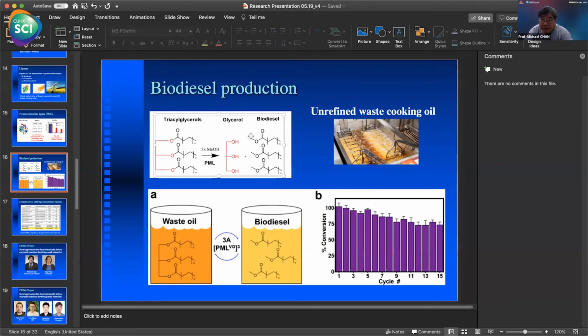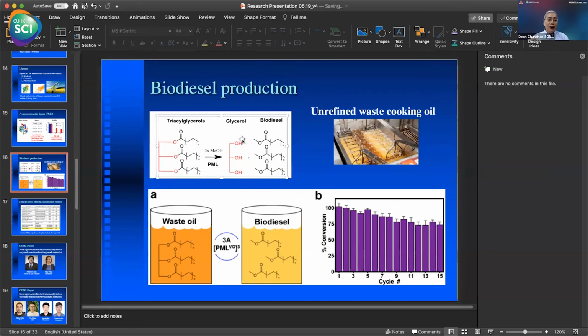It's an ester. You produce glycerol, right? Yes, glycerol. You basically add the methanol to here, and then you basically lose the glycerol, and you have a methyl ester of the fatty acid. Okay, I see. You are producing methyl ester. Well, I see that with the carboxyl group and also the trihydroxy group in the glycerol, wouldn't that actually bond to your PML, causing to lose them gradually, rather than just an oil-water interface?